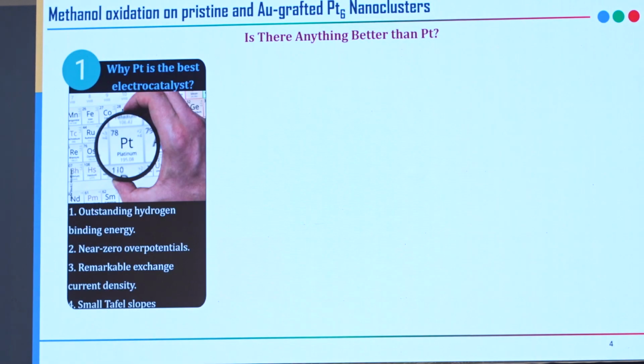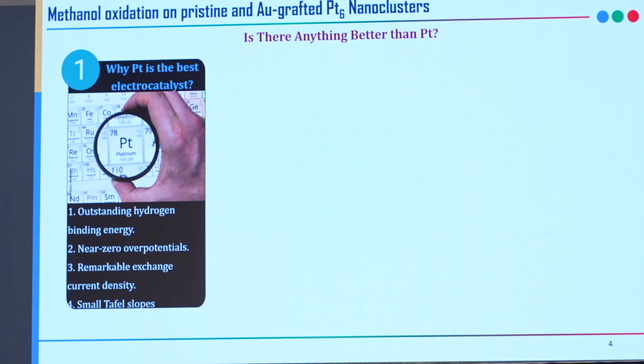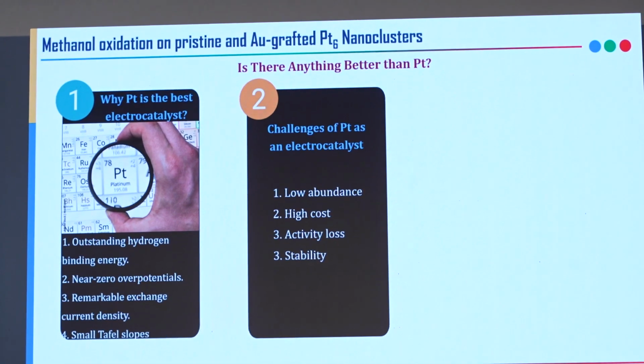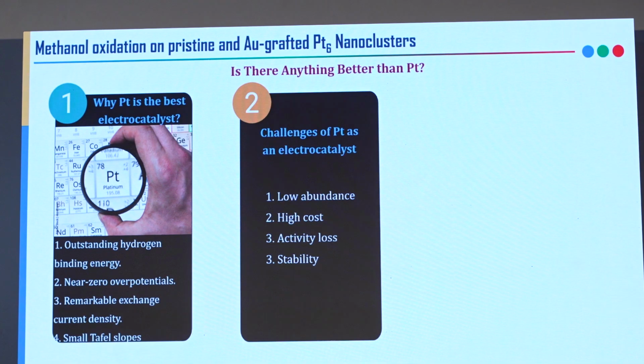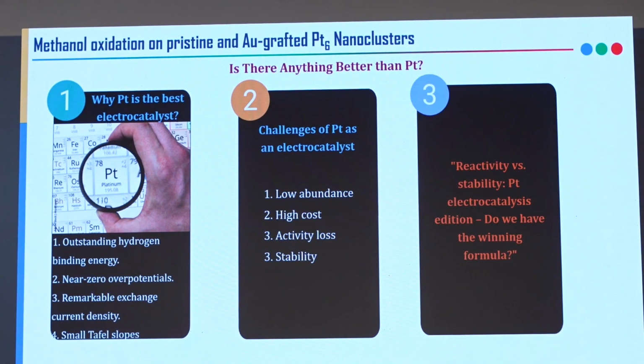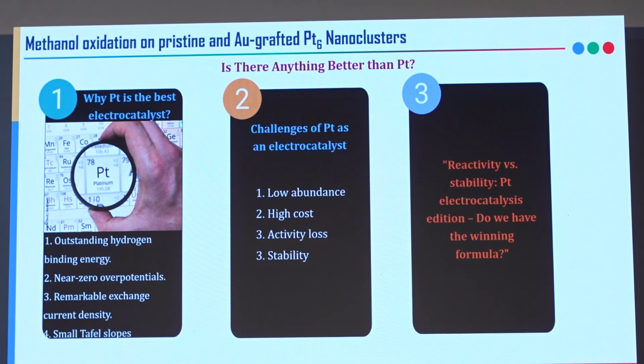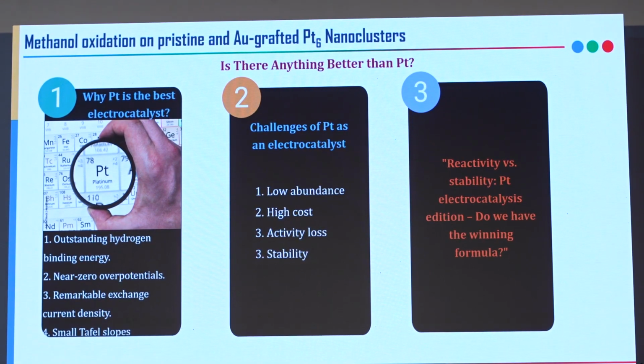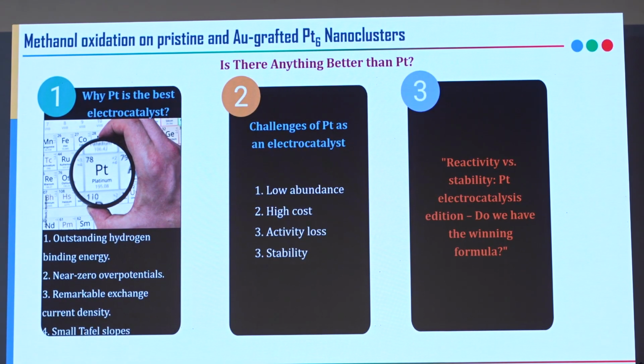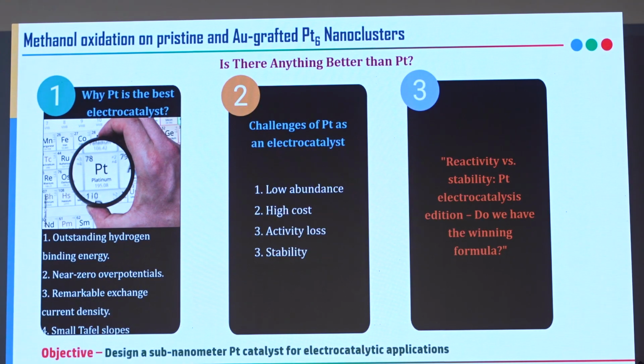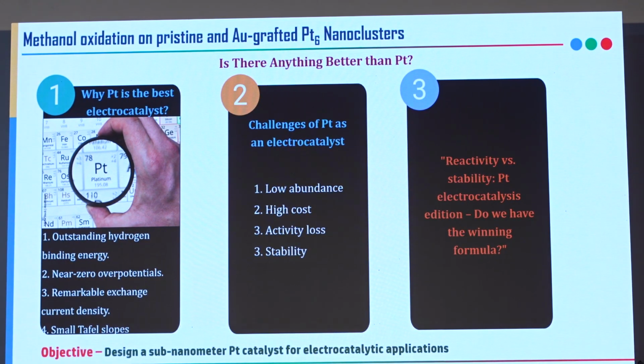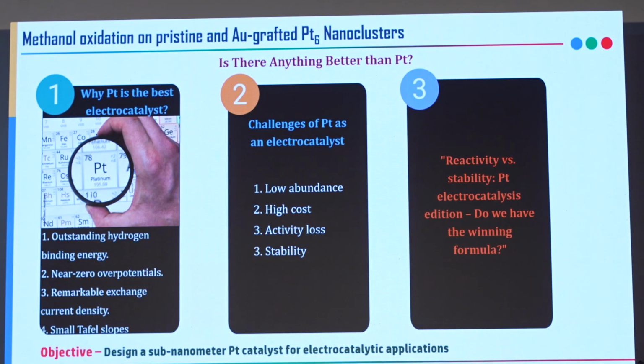In the field of electrocatalysis, platinum holds a paramount position due to its exceptional energy of interaction with hydrogen, low Tafel slope, exchange current density, etc. But the problems are its low abundance, high cost, activity loss and stability. So platinum needs atomic level engineering in order to increase its reactivity towards electrocatalysis. So we have designed sub-nanometer platinum 6 nanoclusters, which we synthesized